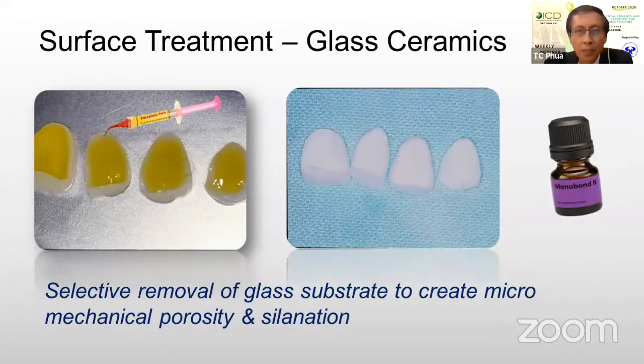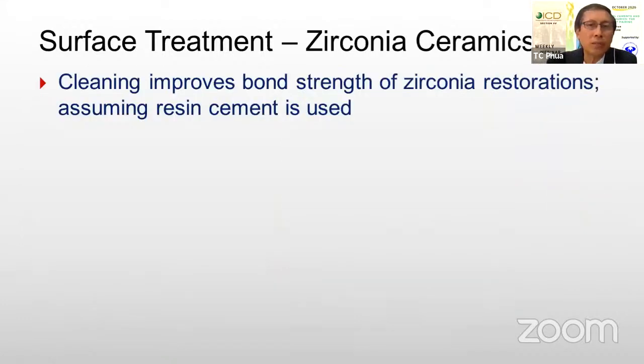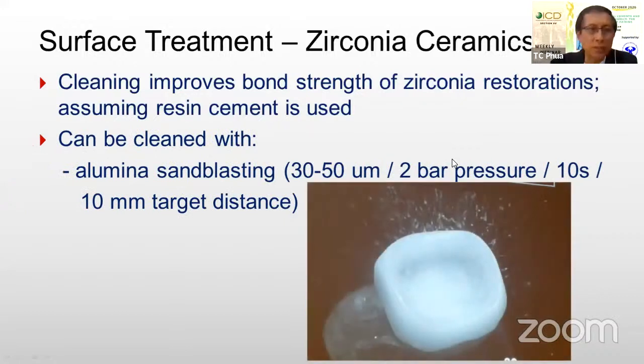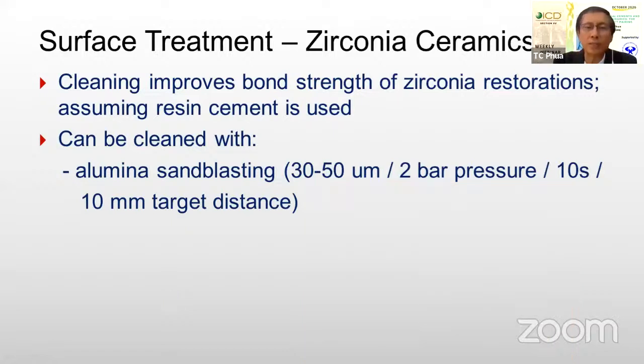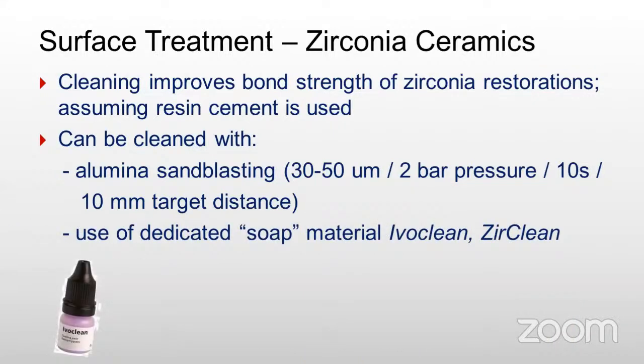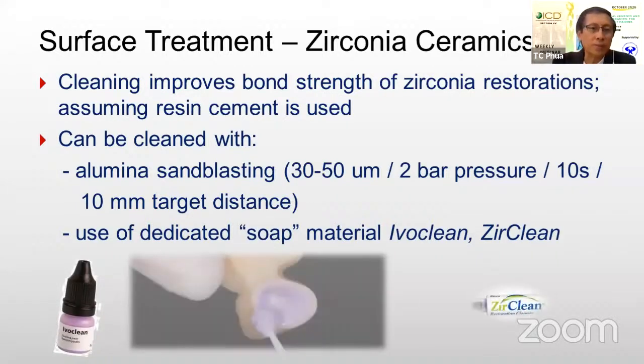Yep, there you go. So if you have selectively removed the glass, you need to silanate it with a wetting bond, like a bonding onto the ceramic, a silane. When we work with zirconia ceramics, as we talked just now, cleaning improved the bond strength of zirconia restoration, assuming resin cement is used. And the cleaning for zirconia is aluminum oxide sandblasting at a specific 2 bar pressure. So we're not using very aggressive sandblasting over here. And you can use a dedicated soap material like Ivoclean or Zirclean from Bisco.